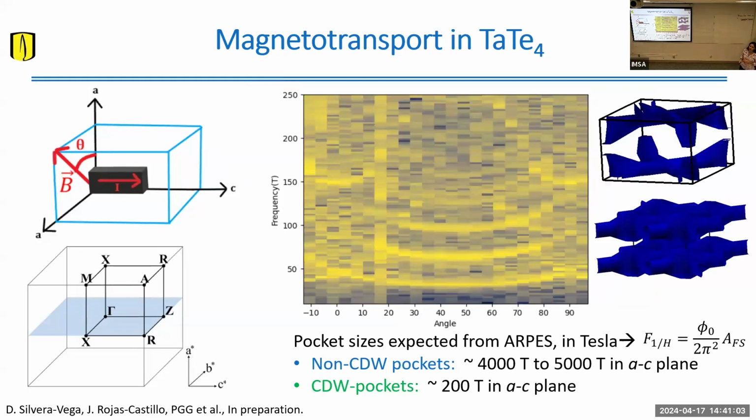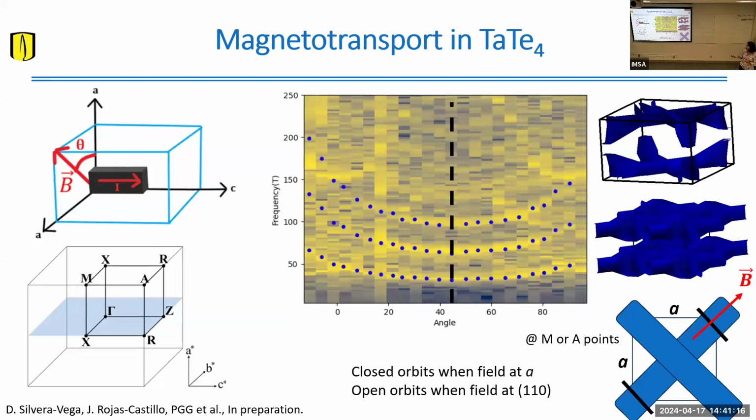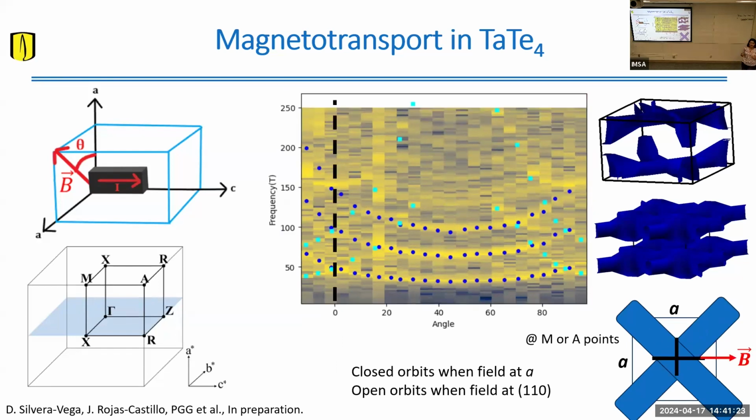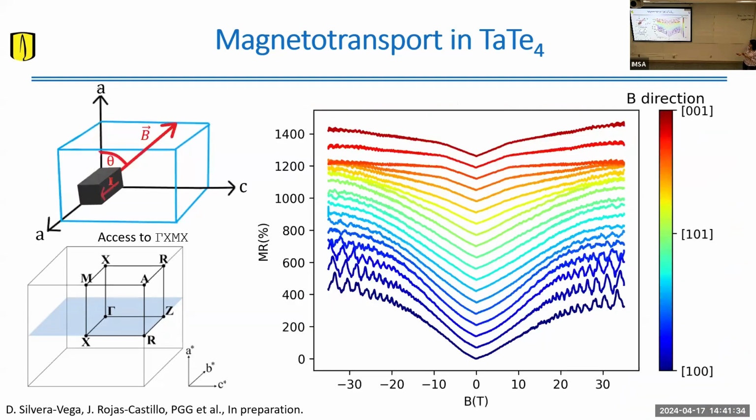So you see many, many features that imply a very complicated Fermi surface. For instance, there is this Fermi surface which actually creates closed orbits in some directions, but open orbits in different directions. So it's really assembling a puzzle to deduce this Fermi surface for this compound. But I think we have been pretty successful at determining what the Fermi surface looks like, because we can map all the different frequencies that we observe into the DFT calculation. So that worked very well.